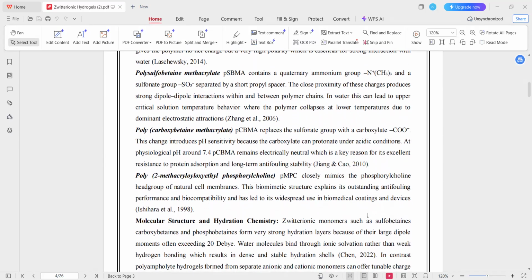While the next monomer is poly(carboxybetaine methacrylate). In this polymer, the anionic group is carboxylate instead of the sulfonate group found in sulfobetaines. This structural difference introduces pH sensitivity into the material. At physiological pH, which is approximately 7.4, the polymer remains electrically neutral, maintaining strong hydration and showing excellent antifouling performance. However, under acidic conditions, the carboxylate group can become protonated. This protonation slightly alters the internal charge balance of the polymer, which in turn affects the swelling behavior. Because of this controlled pH responsiveness, carboxybetaine methacrylate is particularly valuable for medical applications, where materials are often exposed to varying pH environments.